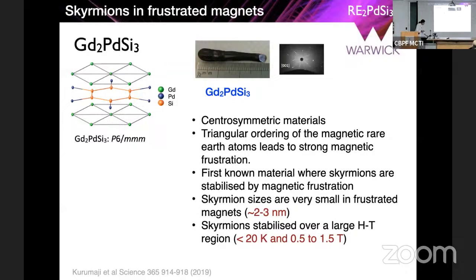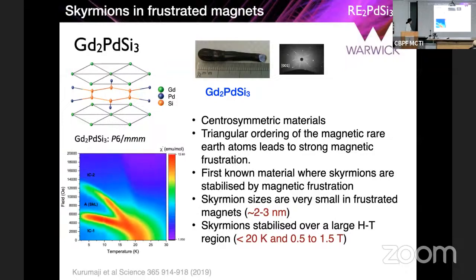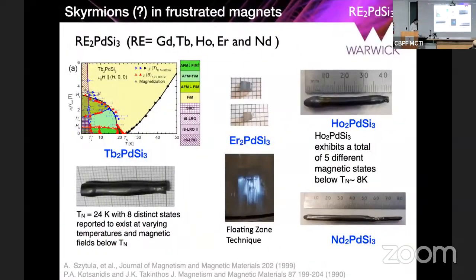But what's interesting is that the skyrmions are proposed as being stable over a very large region in the HT phase diagram. So it's below about 20 Kelvin and in the field region marked here. So it's a very, very large area, not a tiny pocket like the ones that you saw earlier. Okay. So the existence of skyrmions in this was proposed using anomalous Hall effect measurements.